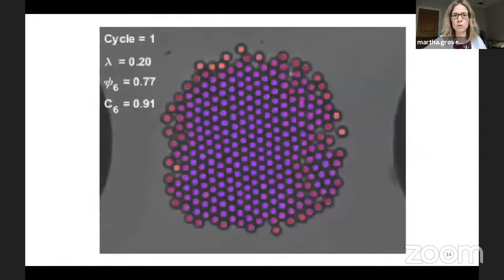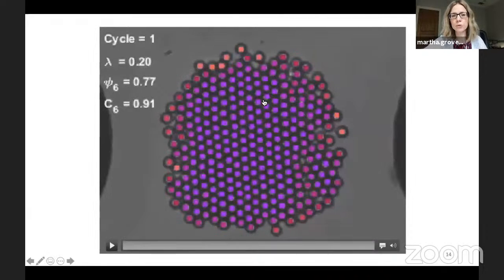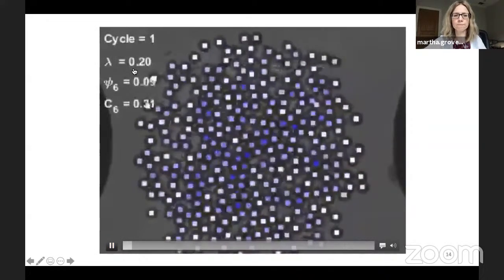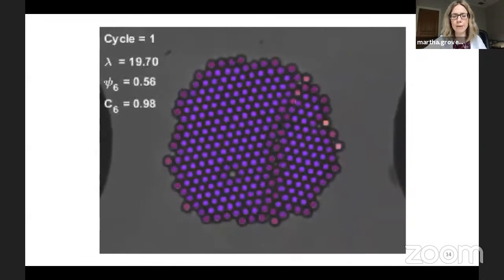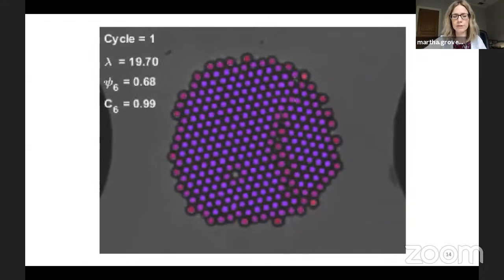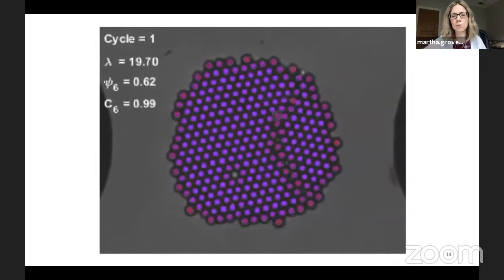This is an experimental movie, but the color represents the C6 value, the local order of each particle. Does it have 6 nearest neighbors in a hexagonal lattice or not? Lambda is the scaled applied voltage. So now we melt it with a low voltage, and then we push hard, but we get a grain boundary. We also have a void. Okay, so it's kind of working its way out slowly.